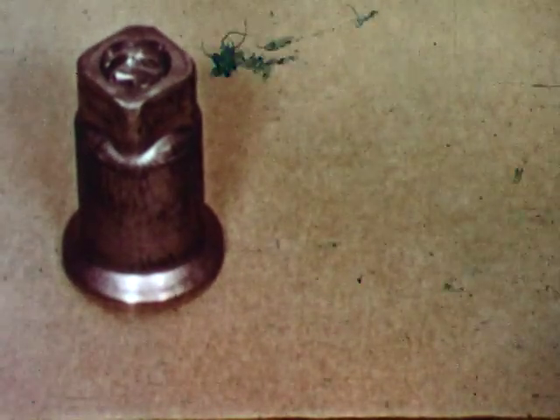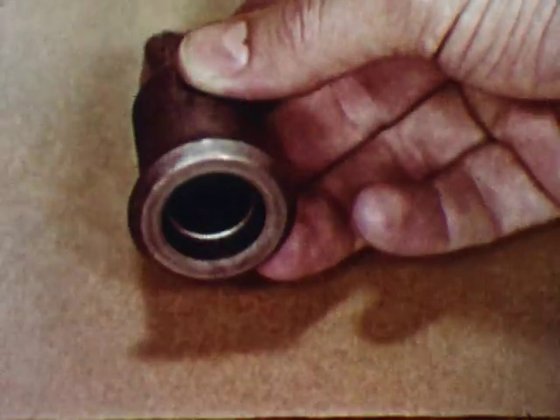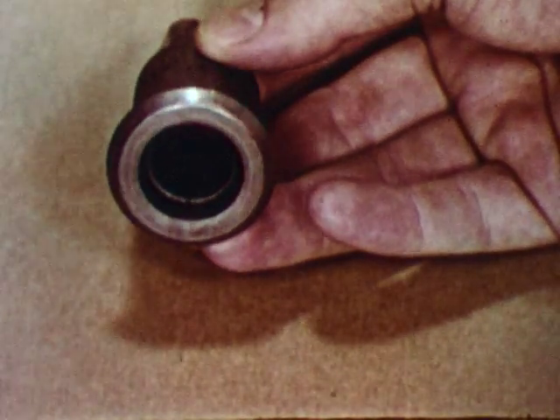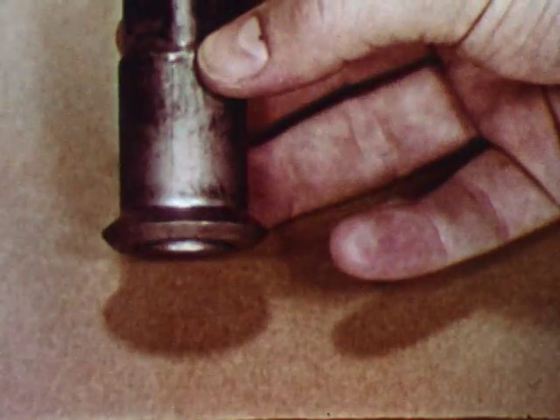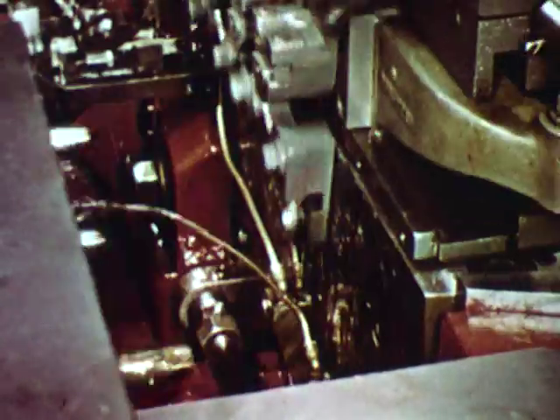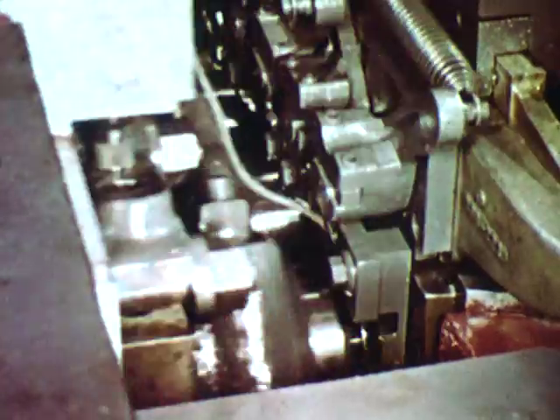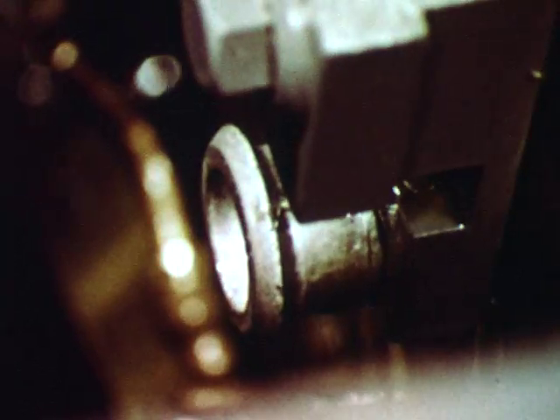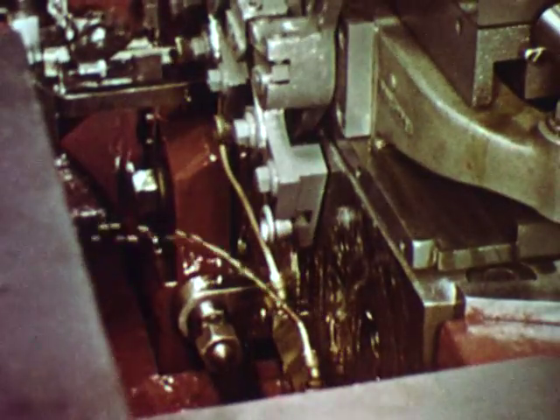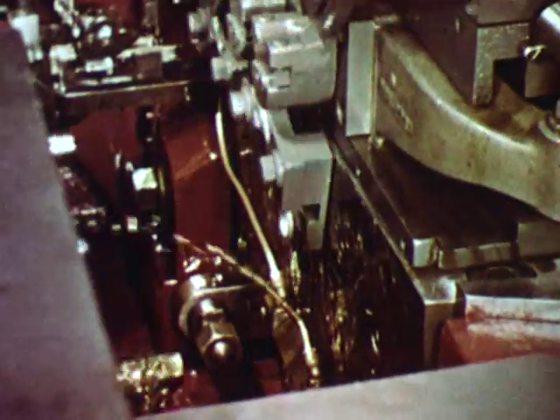This truck wheel nut is made on a 3/4 3-die progressive header from 1018 steel wire at 50 nuts per minute. This is an example of extruding a hollow part. In the first die, the blank is dimpled. In the second, the flange is formed, and in the third, the extrusion forms the hole in the square end. This part was originally made by machining an 18-ounce blank. Cold forming needs only 6 ounces of stock. After the extrusion, the part is carried back on the punch. A stripping mechanism removes the part. To complete the nut, it is threaded inside and out.